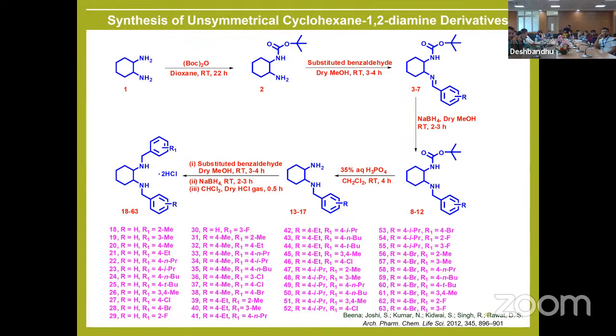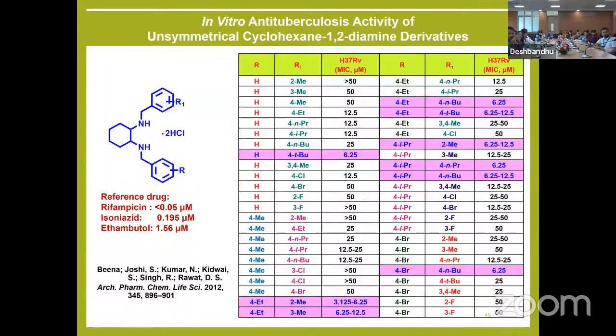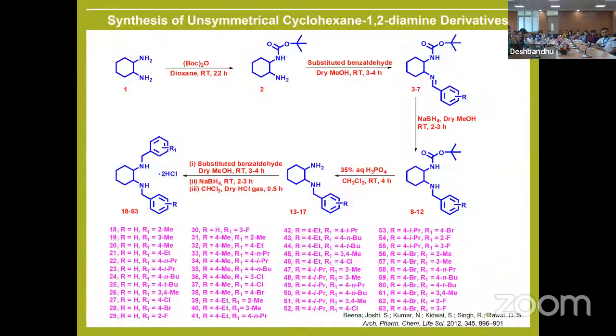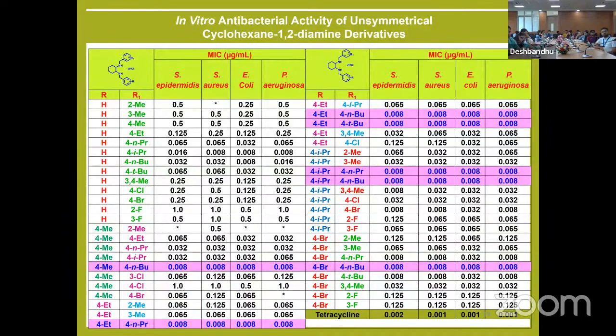Then, based on the promising activity of these compounds on different bacterial strains and mycobacteria, we designed unsymmetrical molecules so that we can have a better structure activity relationship. For that, again, we took cyclohexane diamine, where first one of the NH2 groups is protected and then treated with one benzaldehyde. Then after deprotecting the NH2, we treated with another benzaldehyde, and we could get a series of compounds. These compounds were tested for their activity against various bacterial strains, and very good activity was observed.